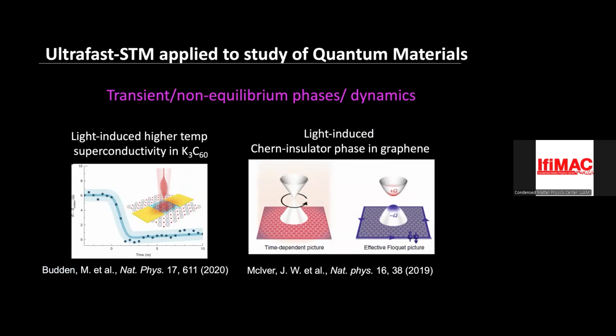Really, what inspired us was this idea of light-induced superconductivity. So there have been all these reports that you can take a superconductor, and if you shine some pulsed laser light on it, for a short time after you illuminate the system, you can get superconductivity which goes to 2 times or 3 times the transition temperature. And in fact, there are some suggestions that you can even take a material that's not superconducting, maybe very close to superconductivity, and bring light-induced superconductivity at pretty high temperatures. So this is one of our inspirations.